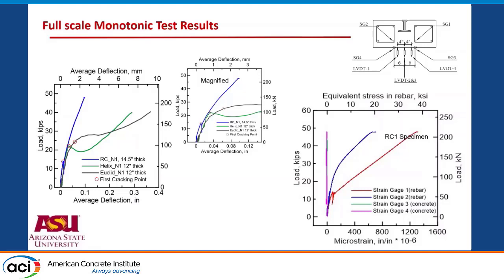So you can see that the reinforced concrete cracks, but the samples with the fibers go much, much higher in terms of their cracking potential. So there is a contribution of the fiber to the crack propagation, meaning that the first main crack, that is the initiation of the load transfer, for the unfiber-reinforced mix is going to be much, much lower, meaning that the steel feels the load much, much faster. Steel rebars feel it much, much faster than some of the fibers in the sample.